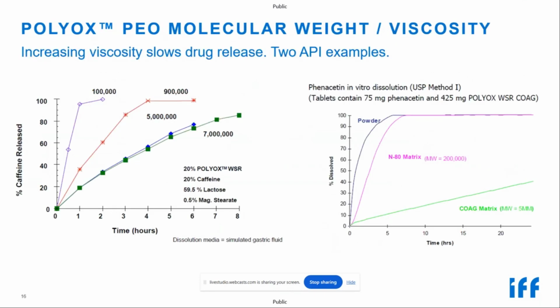For controlled release matrices, the molecular weight of the PEO polymer impacts how an active will release from a PEO matrix. So the molecular weight or the viscosity is controlling the release rate of the active from the matrix. As the molecular weight increases, entanglements increase and increase the gel strength, slowing down the release of the active. For water soluble API, the diffusion pathway lengthens. For poorly water soluble API, the disintegration time lengthens, thus slowing the API release.